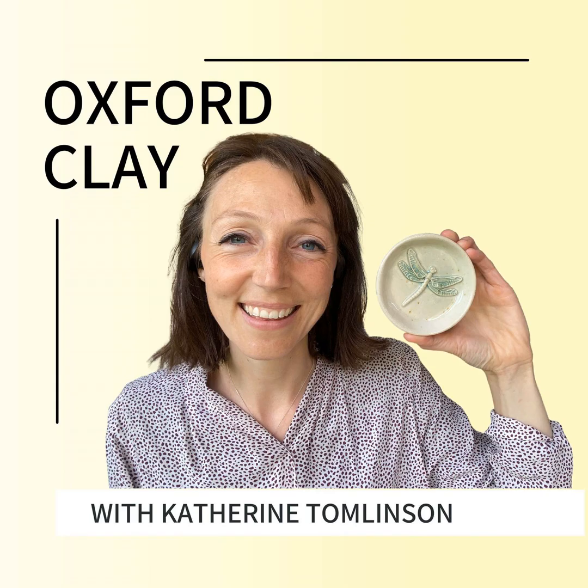And the way I tested this was I tested the glaze on a piece of bone dry greenware, and also a piece of bisqueware. Then I compared them after firing, fired them all up to stoneware temperatures, and saw if there was any difference in the glaze. If the raw glaze one didn't look the same as the one applied to bisqueware pottery, then I thought, oh, it's not suitable because it's doing something strange. But if they looked exactly the same, then I was like, oh, this is great, they're suitable for raw glazing.